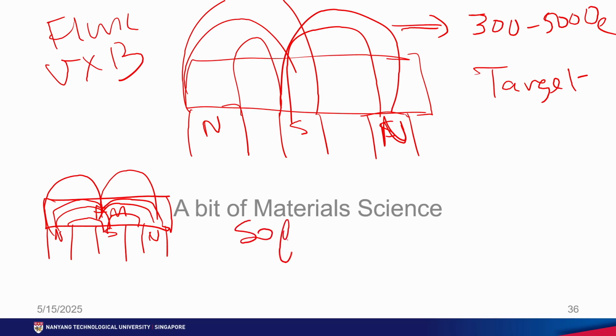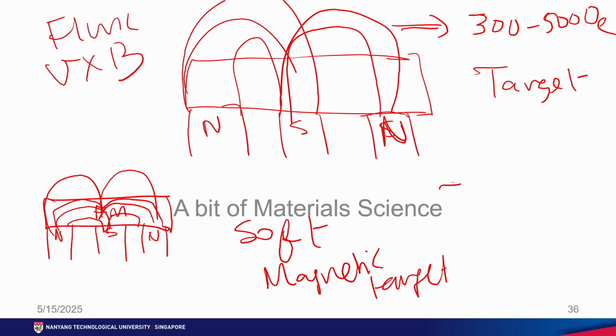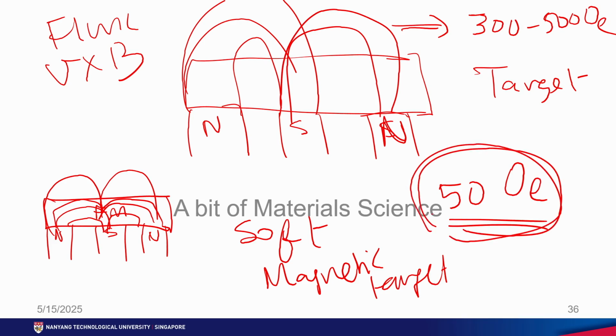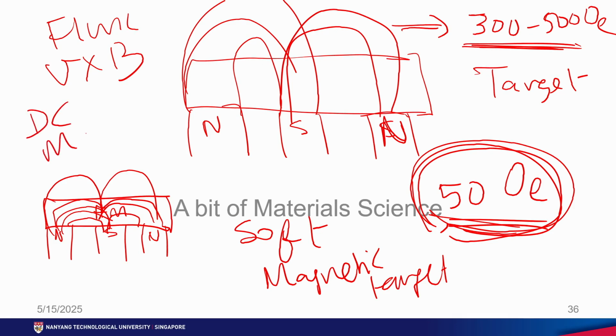On the other hand, if you use the same magnet and a soft magnetic target, here if you measure the field on top of the target, you will see that it's like 50 oersted or something like that. Okay, very low field above the target because of the permeability of the soft magnetic target. Okay, the soft magnetic target conducts all the flux through the target itself, so nothing comes out, so the field is very low. So because this field is very low, you cannot sputter. So typically we need around 300 oersted or more to achieve good DC magnetron sputtering.